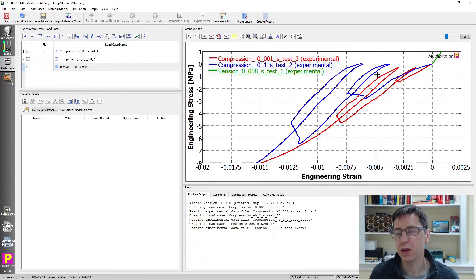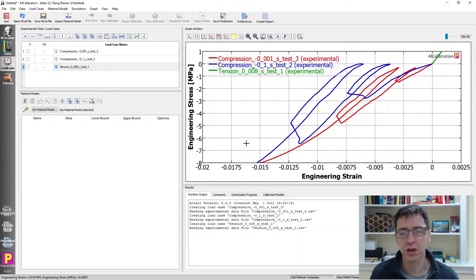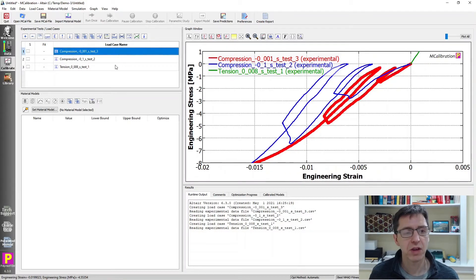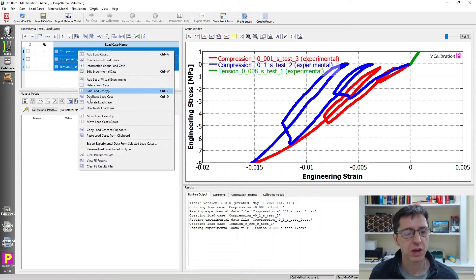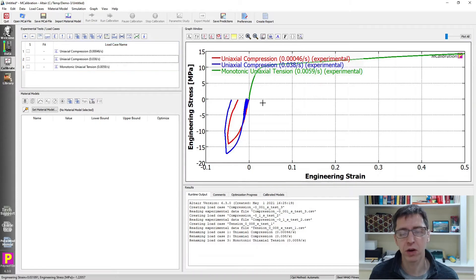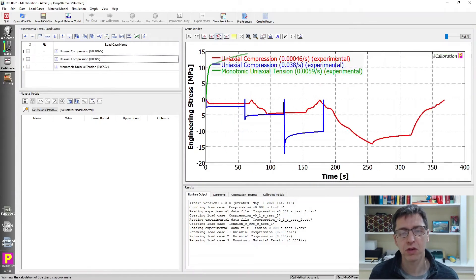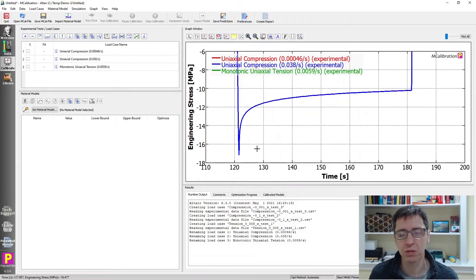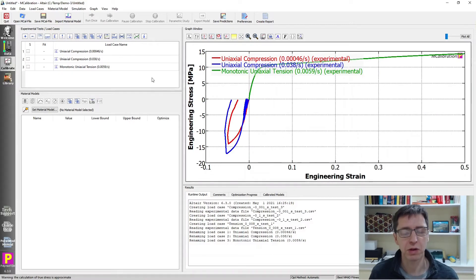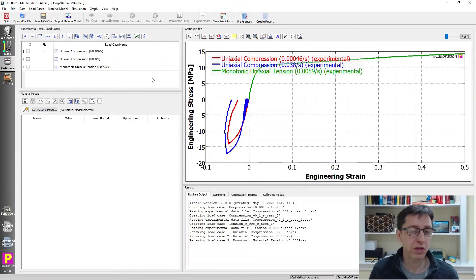If you zoom in on this window, you can see that the data is a little more interesting than it first looked. We have cycles — we load and unload the material a few times at smaller strains to probe the viscoelastic relaxation at different strain rates. Plotting stress versus time shows just how much this material relaxes — about a minute or so of relaxation, and it relaxes a lot. That's pretty common for many polymers. With mCalibration, it is just as easy to calibrate a viscoelastic material model as it is to calibrate a hyperelastic or plasticity model.